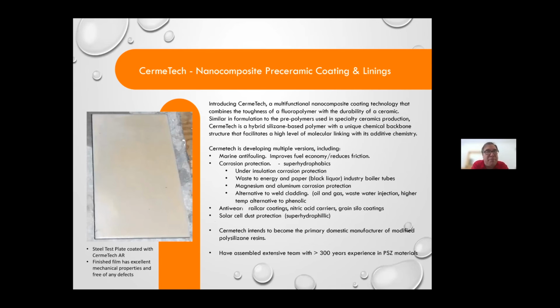Moving on, one of our newer starts: we've done considerable work over the last 25 years in ceramic extreme environment materials, pre-ceramic polymers. We've collected a lot of the experts in polysilazane chemistry and are launching CermeTech. This is some work that came out of the oil and gas industry, providing corrosion and wear protection at elevated temperatures. It started at 400 Fahrenheit and it's now up to 600 Fahrenheit in some applications. This is a tailorable material based on polysilazane compounding. It can provide extreme wear resistance for abrasion, and is extremely resistant to a lot of corrosive environments, particularly oxidizing systems, so sulfur, sulfuric acid, nitric acid, in applications at high temperatures. There are versions of this that are stable up to 600 centigrade and above.